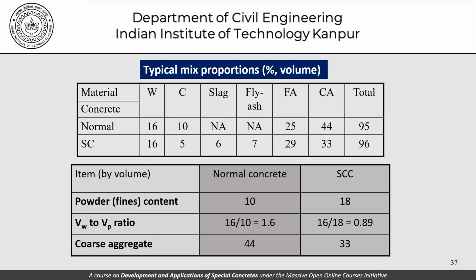Looking at those numbers by volume, you get these values here, and from there if we translate to the discussion that we were having in terms of powder content, that is the fines content, in normal concrete it's only about 10%, which goes up to 18% in this particular illustrative example of self-compacting concrete mix. As far as the water to powder ratio is concerned by volume, it's about 1.6 here and is as small as 0.9 here. The coarse aggregate content from 44% has gone down to 33% as far as the volume of coarse aggregate is concerned.